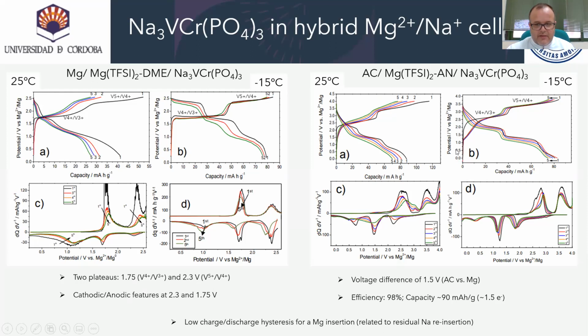The efficiency is around 98%, and the capacity is assigned to 1.5 electron, implying a multi-electron reaction and the activation of the vanadium 5, vanadium 4 redox couple. The low charge discharge hysteresis for a magnesium insertion is related to residual sodium reinsertion from the initial structure.